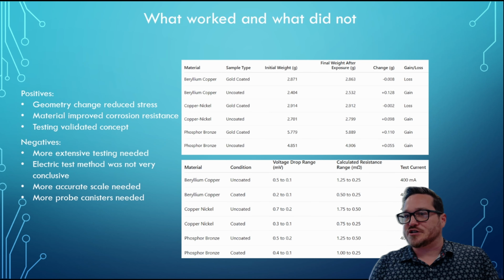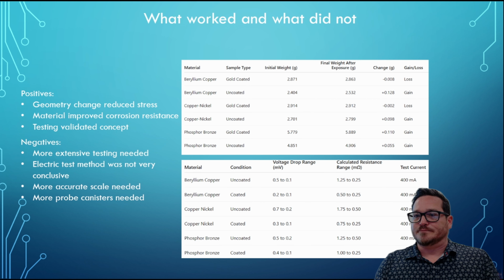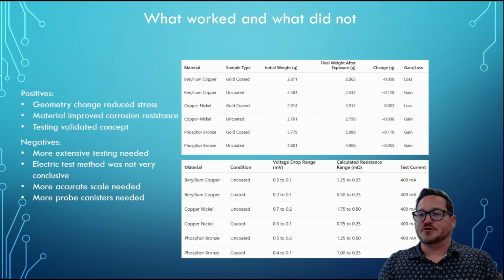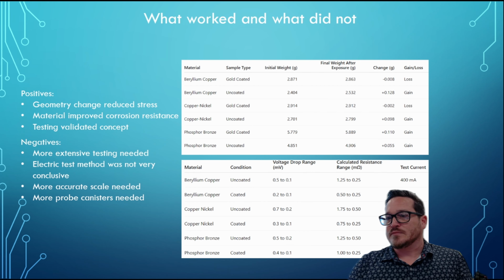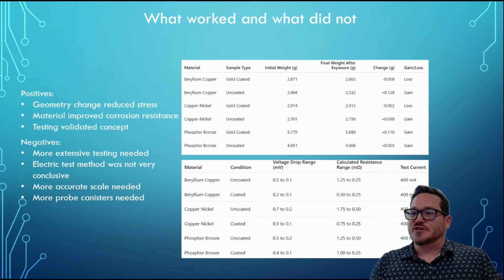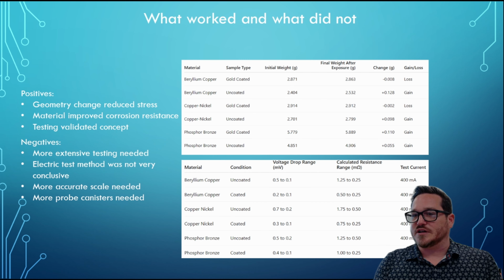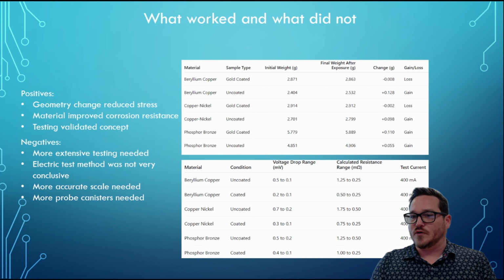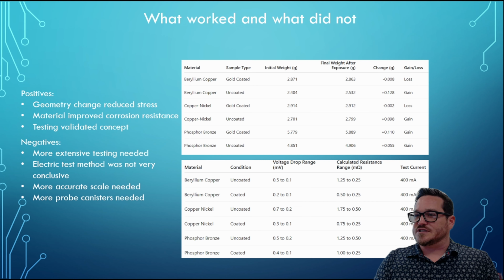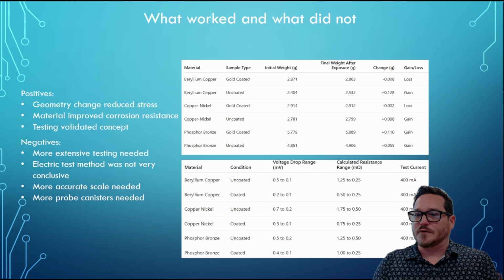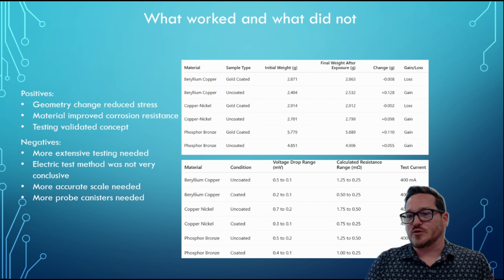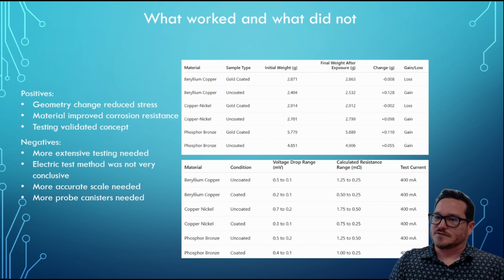These are the aspects of my project that worked and what did not work so well. The geometry changes made to the contact pins did seem to have a positive effect on reducing stress to the pins and preventing damage. The new metal pieces showed good signs of resisting corrosion, and the test methods seemed to validate my concepts. However, while the electrical tests showed that the metals maintained electrical continuity, the voltage readings were somewhat erratic, and it was difficult to discern if there were voltage spikes or just difficulties with the testing method itself.